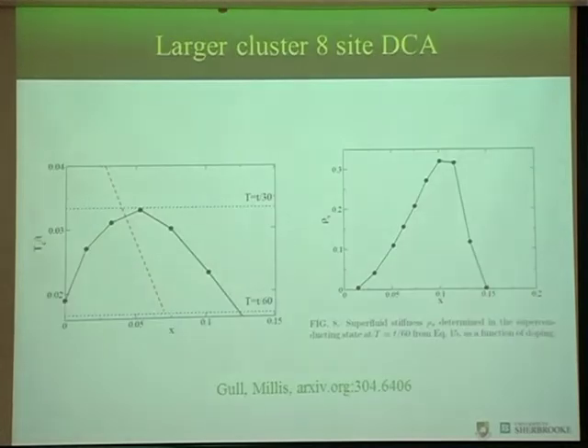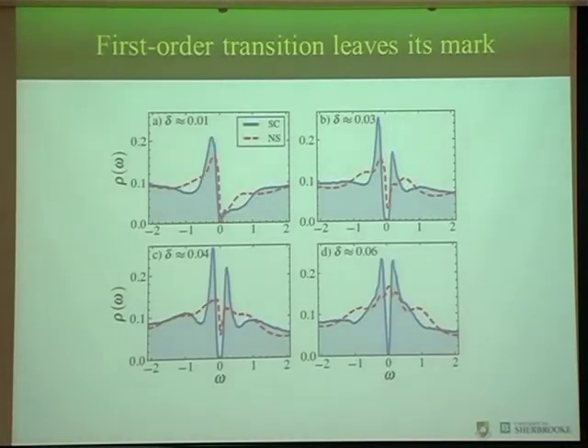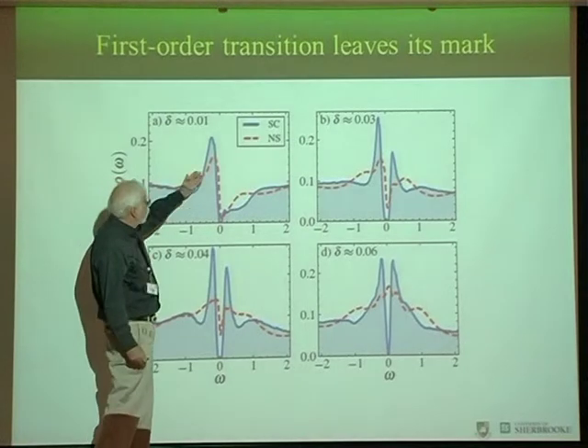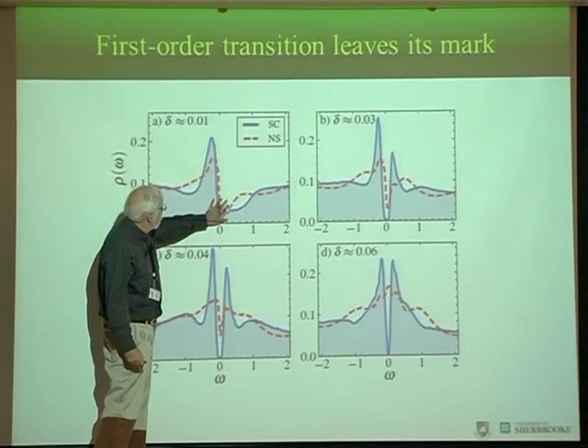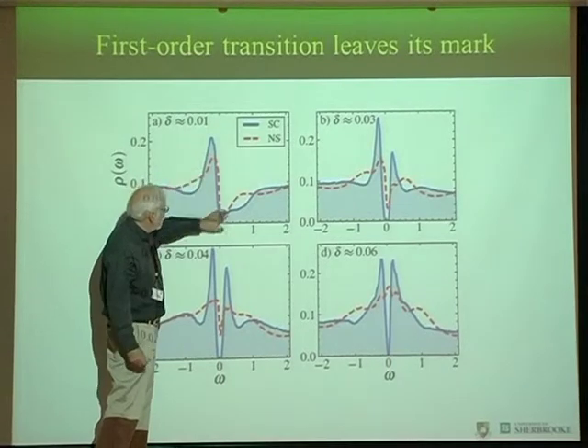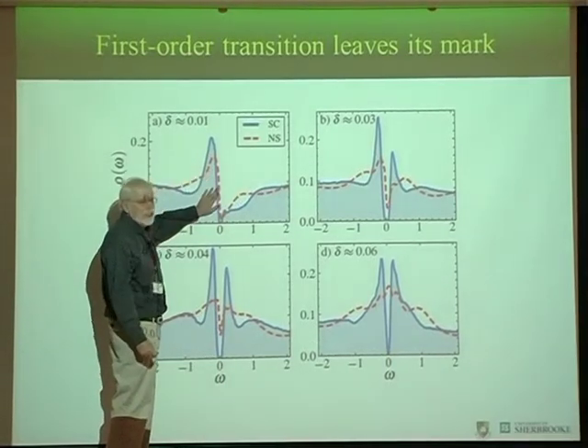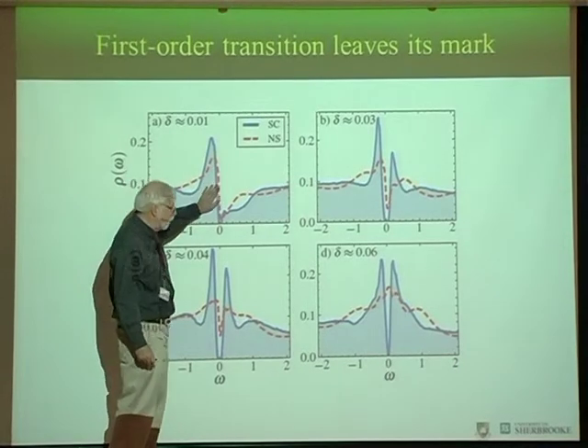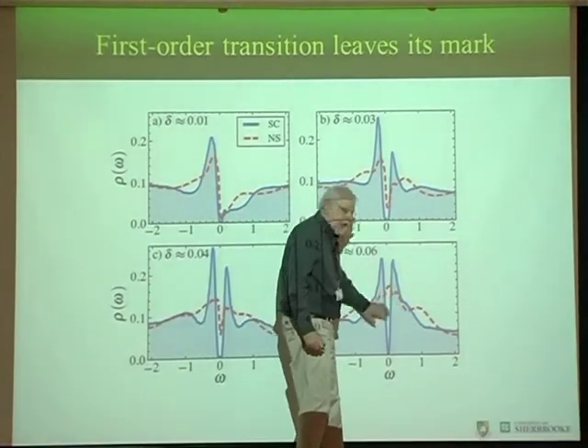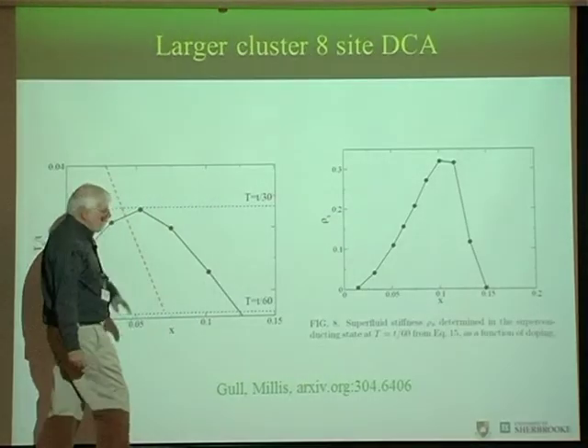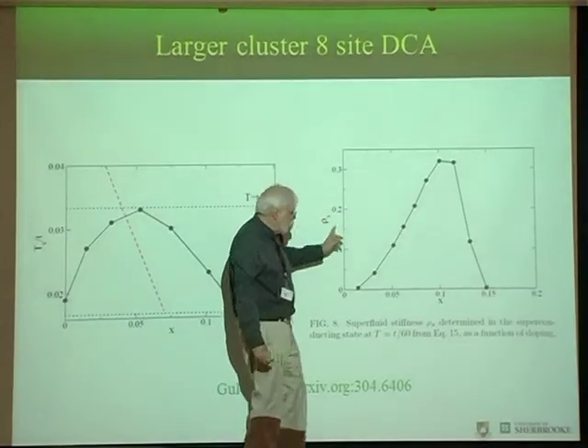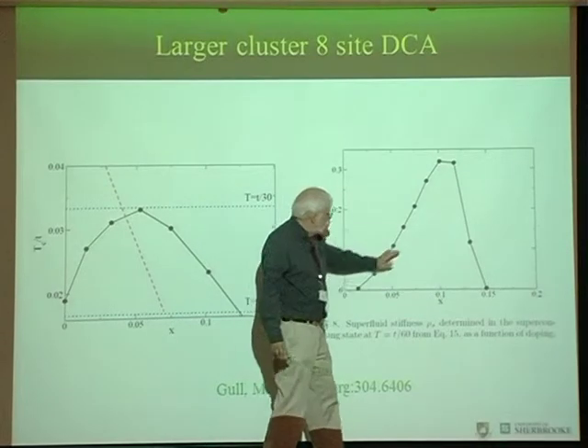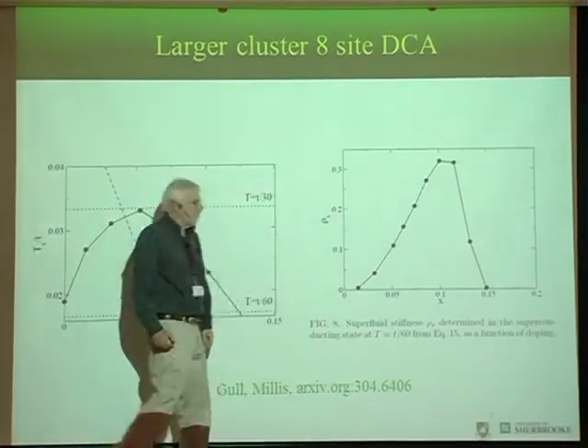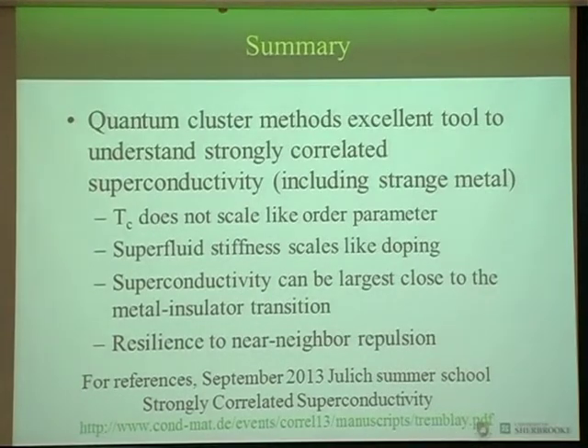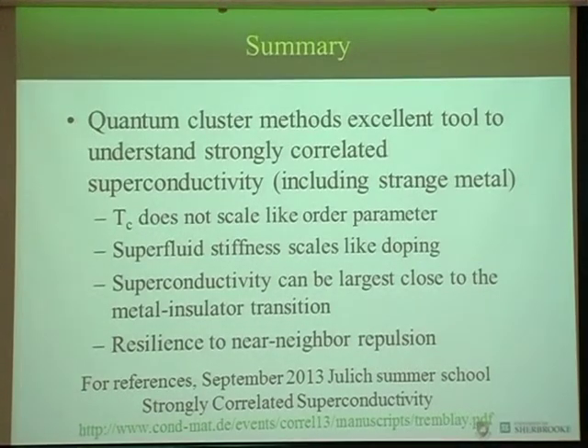I'm just going to perhaps show that the density of states in the superconducting state in the highly underdoped case is very asymmetrical, like the normal state. So the superconducting state remembers the normal state. It's not a simple BCS superconductor. It becomes more electron-hole symmetric at large doping. And this is a result from Andy Millis's group, where rho S as a function of x, again, scales with x at small doping. C-axis, sure, yeah, important. Otherwise, you could neglect the vertex corrections.